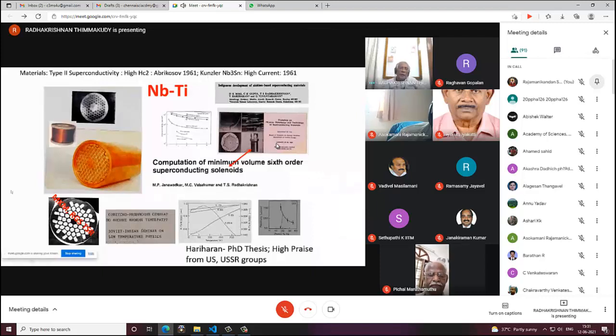By that time it was known in Rutherford in England that if you make a superconducting wire and make it a magnet, it will not be stable. It can of course carry high current in the non-magnetic state, that means if H is equal to 0, but as you apply a magnetic field, there will be a J cross H Lorentz force, and that will destabilize it. That's because the vortices I talked about will start moving, and that causes dissipation.